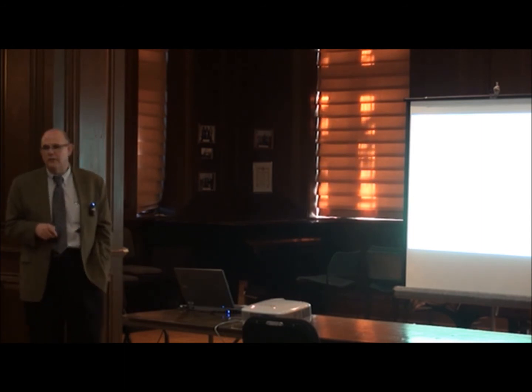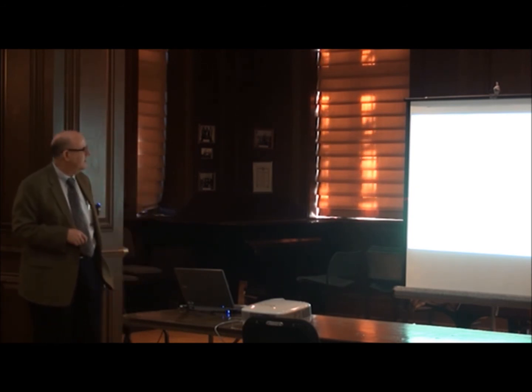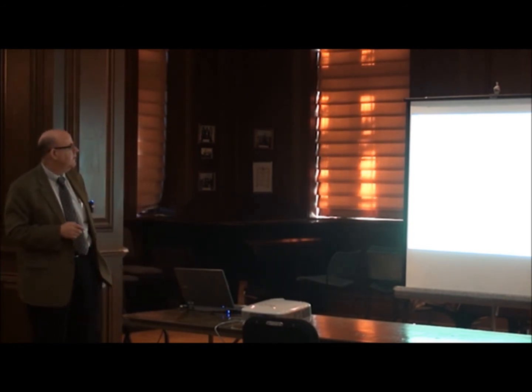The idea is that I'm moving this bottom surface relative to the top surface, which is tilted and so forth. If I have texture in the direction of motion, I call that longitudinal roughness. If I have texture perpendicular, I have transverse roughness. And there's a parameter that defines that, this gamma parameter. It's defined to be infinity in longitudinal roughness, and it's 0 in transverse roughness. And there's a simple way of calculating this based on autocorrelation functions. But this is pictorially what we're getting at.